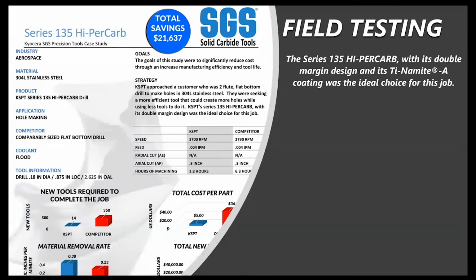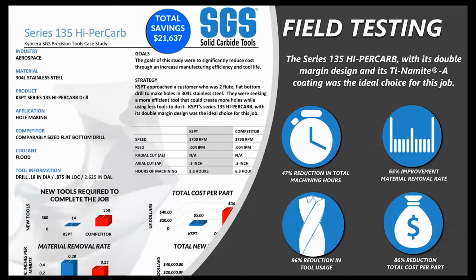So this final case study is based on a cost savings we offered a customer in 304L stainless. They were using a competitor's solid carbide drill with flood coolant. Both drills were 3/16 diameter, programmed to take a short .3 inch axial depth of cut. Tool cost was similar, but the running parameters went from 2970 RPM at 3 thou per rev to 3700 at